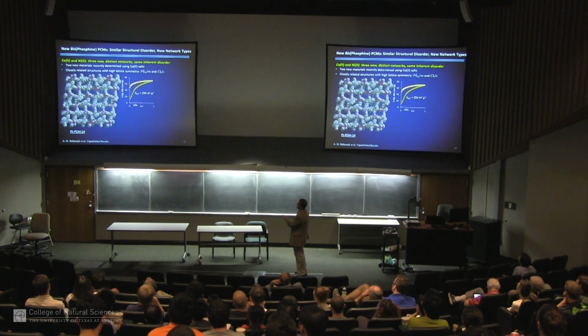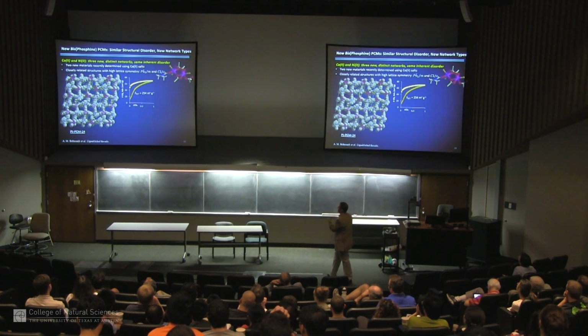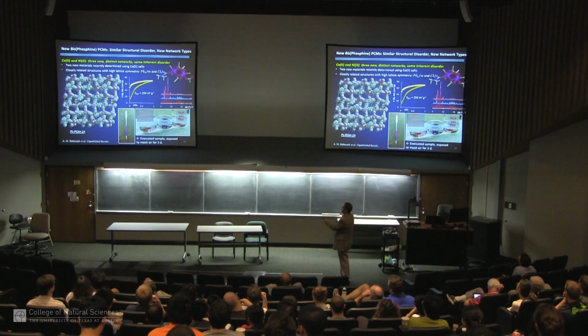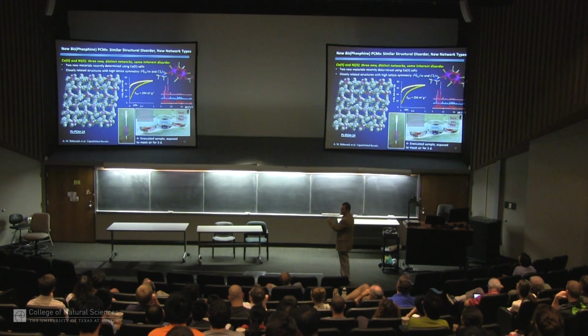And so this is another material with the same building block in a different orientation. Here we have, I think, 4 different pore dimensions. And this one has cobalt instead of zinc in the corners. And these have the water groups again, because we're making them in the presence of water. And those can be pulled off, just as I showed you in the previous example. So now we have activated sites in 2 places, in the corners and in the catalytically active metals. And you can see this cobalt, for those of you who are good at inorganic chemistry, when you remove 2 waters, this becomes tetrahedral, and tetrahedral cobalt is blue, and you can see a reversible color change in the crystals.